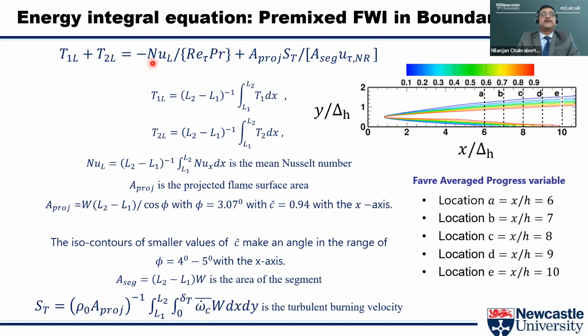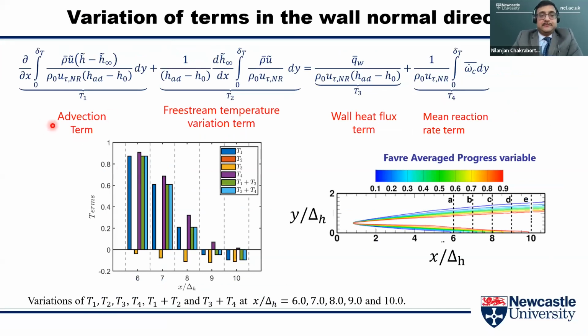Minus sign for Nusselt number because we are actually losing heat through this bottom wall, and that's taken care of by this negative sign. Nusselt number is just the magnitude. So first important thing to notice that we have evaluated each of these terms at these locations, 6, 7, 8, 9, 10, in terms of the streamwise location normalized by the channel half height. T1 plus T2 remains equal to T3 plus T4. T2, the free stream temperature variation term, is negligible in this case, so we can ignore that for this particular configuration at least.